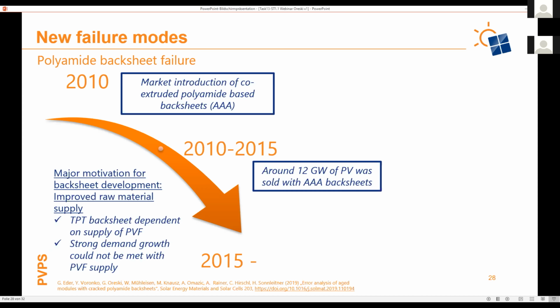There was a problem with the raw material supply for the standard backsheet composition back then, because the so-called TPT backsheet was dominant, and the T stands for Tedlar, that's PVF, polyvinyl fluoride. There is only one manufacturer of this, and there was some sort of market shortage on this material, so there was a big incentive to develop new materials, and that happened.